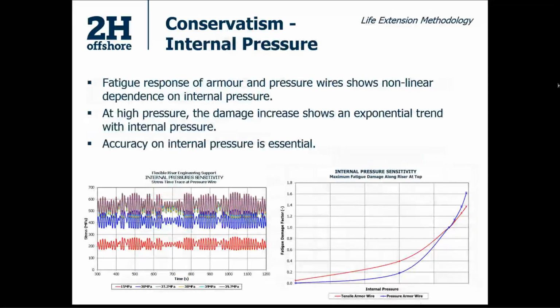Another area of conservatism is internal pressure. So instead of assuming that we have a high internal pressure, we see that as we get higher and higher pressure, the damage increase is exponential. So having accurate internal pressures is essential. So not just taking one pressure and applying it to the whole of the riser, but also looking at what's actually occurring, so taking operating pressures. We see that exponential effect in the plot on the right, but on the left we see that we've got different stress effects at different pressures, obviously increasing in stress as a result of that internal pressure.